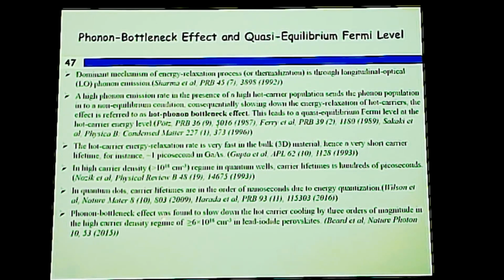So they found that in the high carrier density regime, the phonon bottleneck effect is found to increase the carrier lifetime significantly, by 3 orders of magnitude. So this kind of mechanism, the phonon bottleneck effect, appears to be common under certain conditions, and the condition in our case is low temperature, very low temperature. So to reach high operating temperature, the question is what can we do based on our findings.